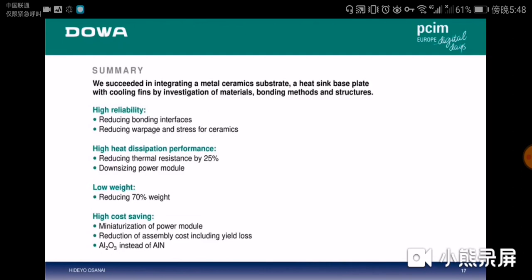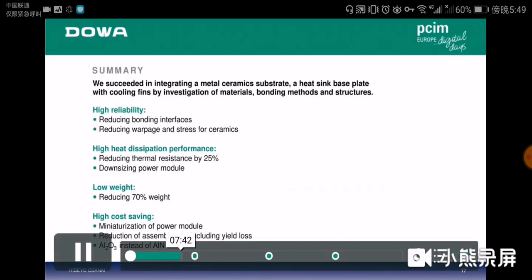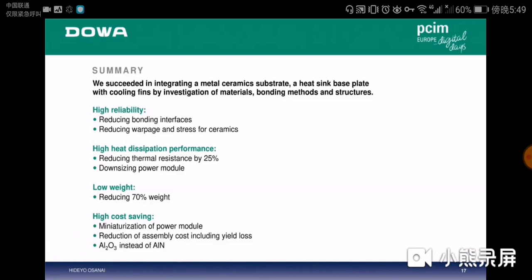Let me summarize the results. We have succeeded in integrating a metal ceramic substrate, base plate, and cooler. High reliability was achieved by using the two-ceramics structure, which enables significantly reduced warpage and minimized principal stress. By eliminating system soldering and TIM, we gained improved heat dissipation of approximately 25% compared to conventional modules using AlN AMB. This enables downsizing of the modules.